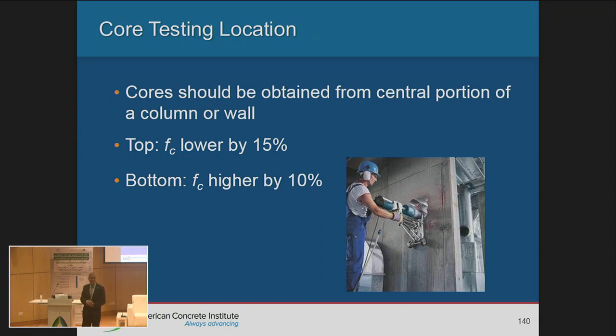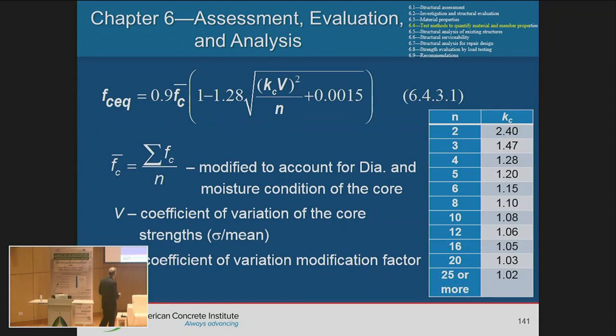And why is that? Because when you place the concrete, most of the aggregates will go down below, right? So you have denser concrete, stronger concrete. And at the top, you don't have much aggregate. You actually have lower quality concrete. So the best thing is to take your cores in the middle.